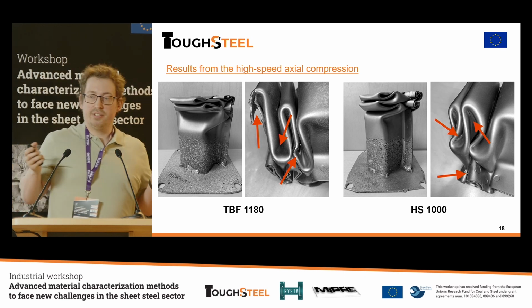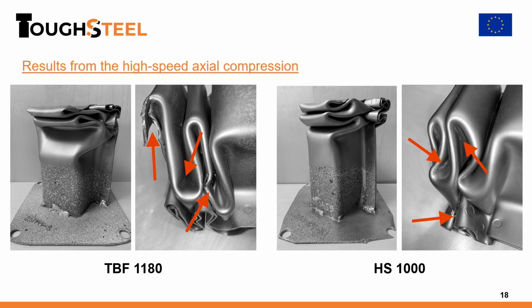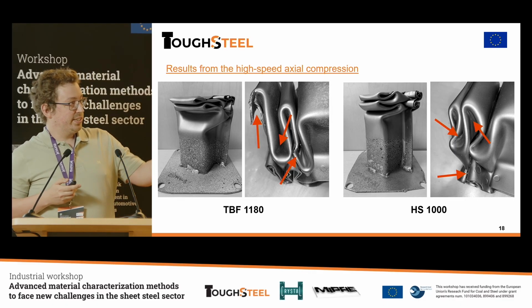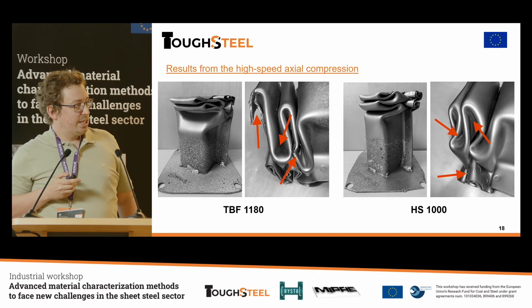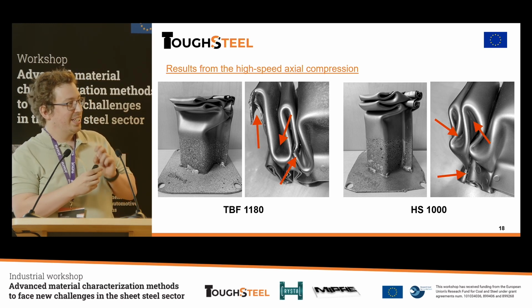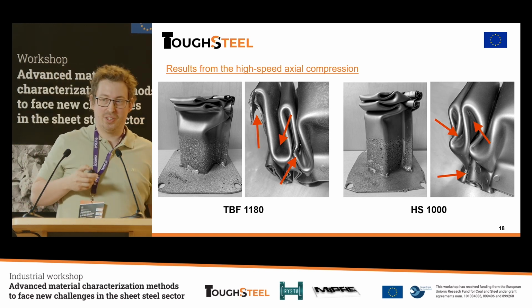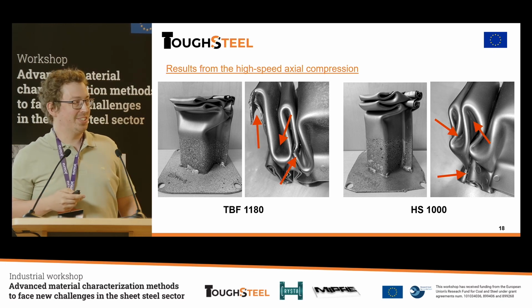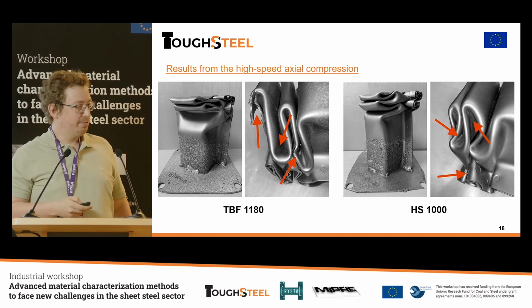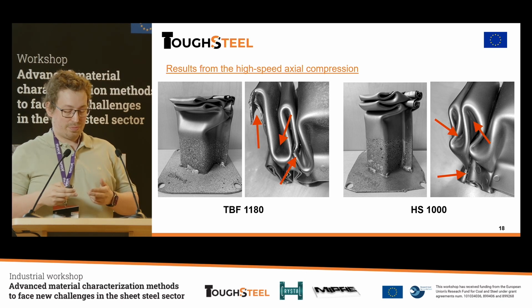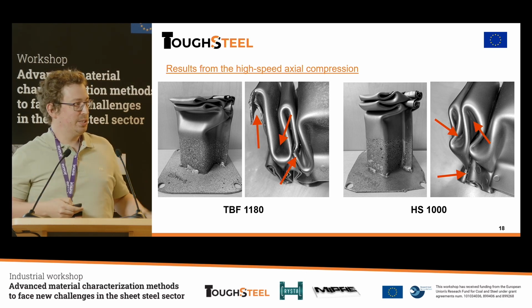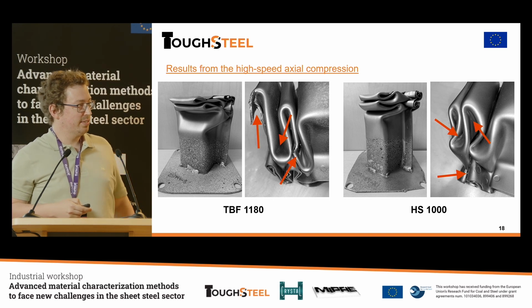And we could have seen this from the beginning because we saw the essential work of fracture values, right? It was higher for the right material than the left material. So we could expect that there should be less cracking and better crash resistance. And we can see that here. And a lot of the cracking for the hot stamping steel was under the folds, hiding in the folds there. So it was much harder to see with the cameras. So we had to be a little bit creative to backtrack from the final deformation and see when we had blowouts and so on to measure or estimate the cracks.